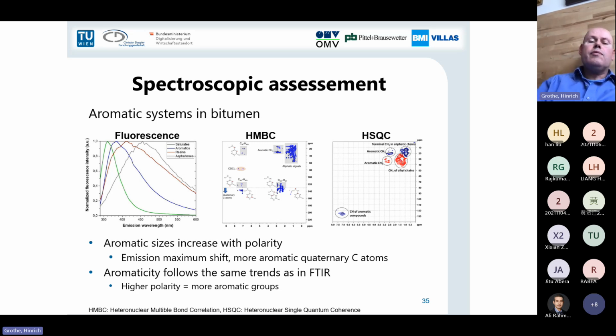And here we can correlate this information with different kinds of NMR spectroscopy. This is correlation NMR spectroscopy, and you might recognize that here you can really nicely differentiate saturates, aromatics, olefinic systems, and aromatic systems. And you can correlate that with your knowledge from the fluorescence and the infrared, and we can really learn and understand the chemistry inside this material. And as I already said, the higher polarity then means more aromatic groups. And this is finally what we learn from the system.